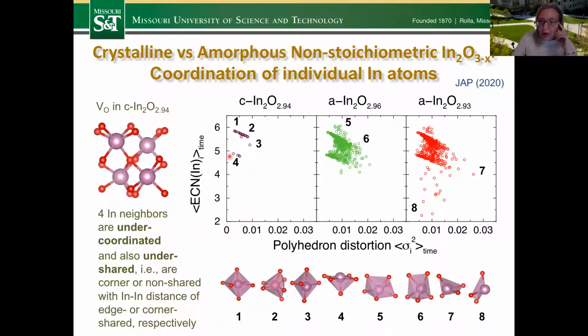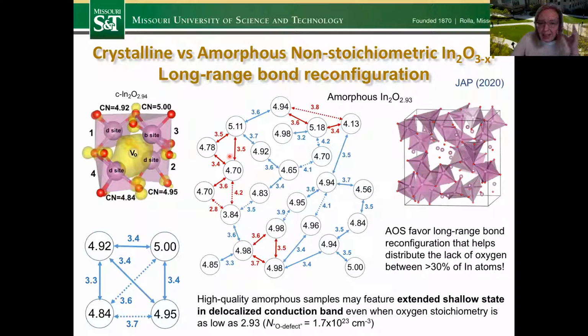So what we find is that the vacancy in crystalline indium oxide looks like this. So we have a strong localization of this. It's a deep defect, in fact, in indium oxide. And we have strong localization of the electrons right there on the vacancy site. So we can schematically show that the vacancy looks like that in the crystalline material.